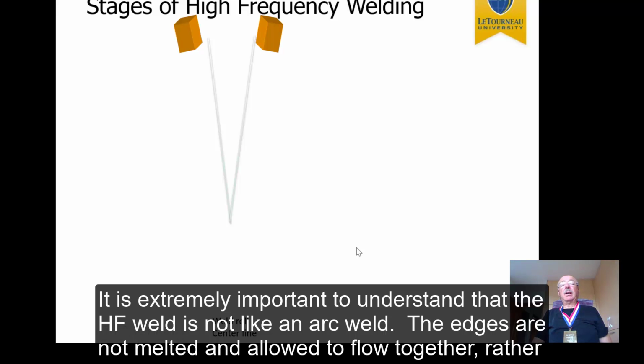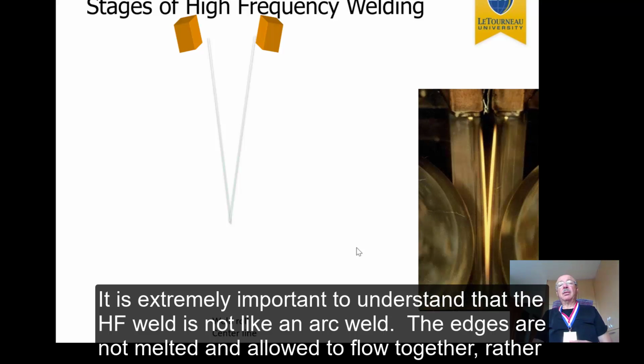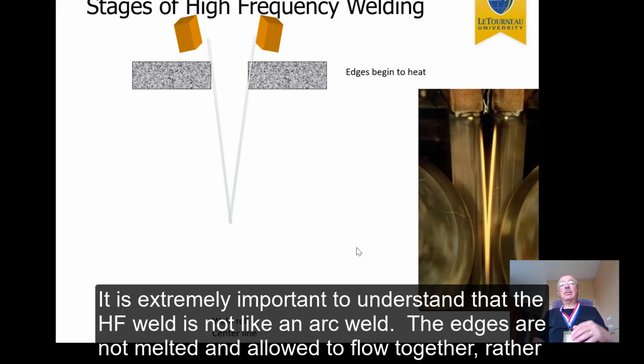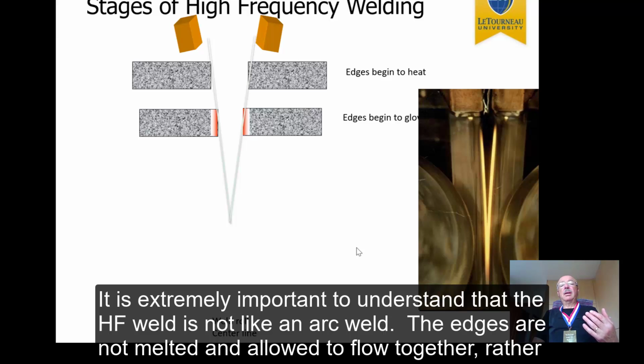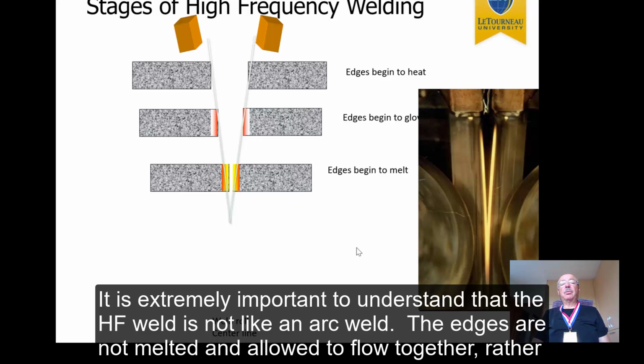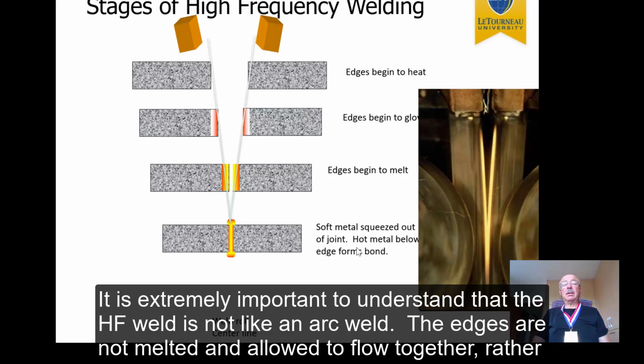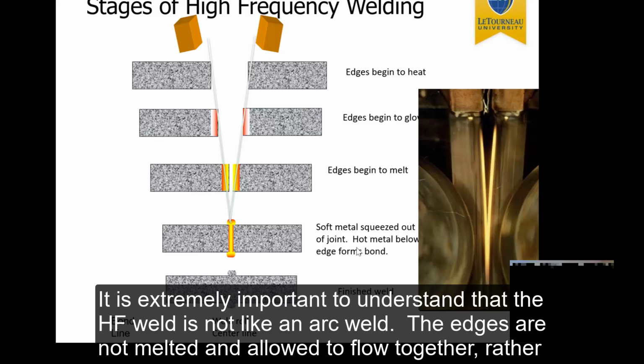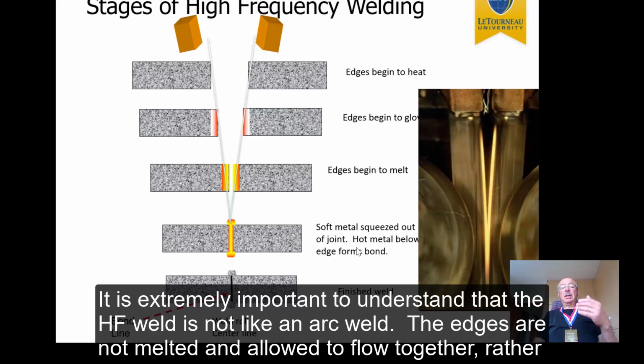So you can basically split the high frequency welding into several stages. At the beginning, the contacts start heating up the edges; these are the contacts represented schematically. When the edges begin to heat, obviously this happens very fast. When they start glowing, which means that they reach a temperature over 1,000 degrees centigrade, we bring them really close to one another. And yes, this is a solid state process, yet the edges begin to melt. So it's really hot when they are squeezed together. Important is that the melted and resolidified material is squeezed out from the interface, and you end up with a joint. And basically, the topic of my talk is the bond line, which is a metallurgical feature you will see in any cross-section along the middle line of the weld.